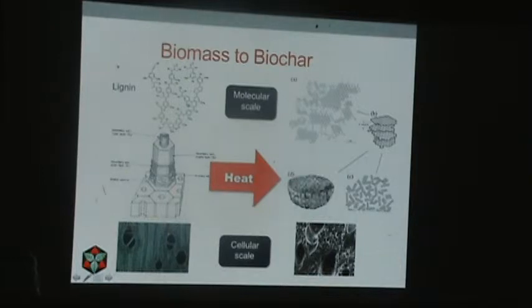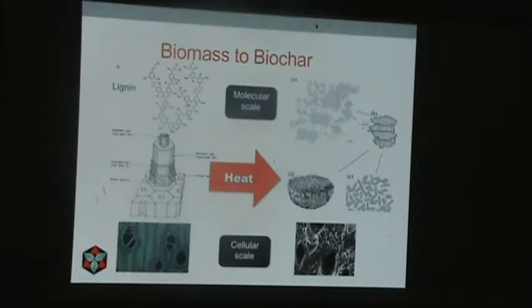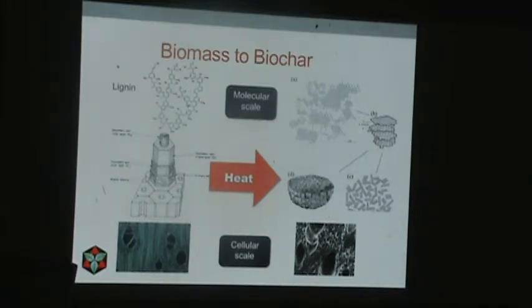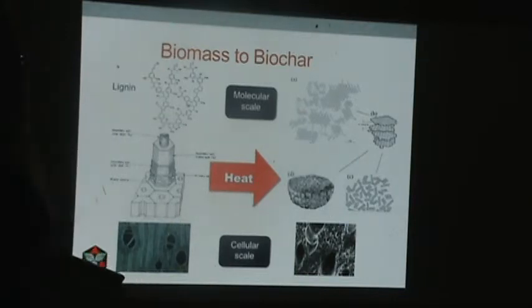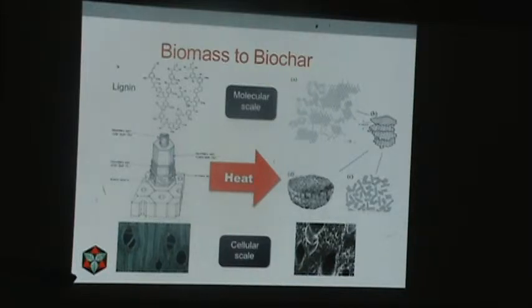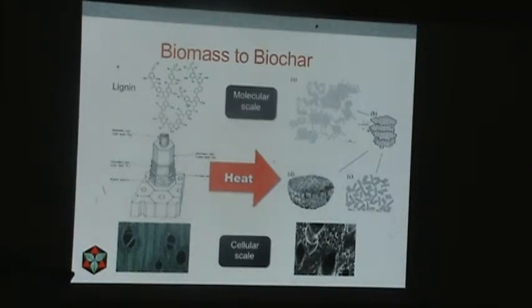The cool thing about it is that at the cellular scale, biochar retains the structure of the plant. If you're using wood, you have the whole vascular system structure of the plant retained. So you end up with porosity at different scales — nano, micro, and macro porosity — which has really interesting implications for life forms colonizing it. It also provides incredible amounts of surface area where different kinds of chemical reactions happen. That's really the key to what biochar is and what it does.